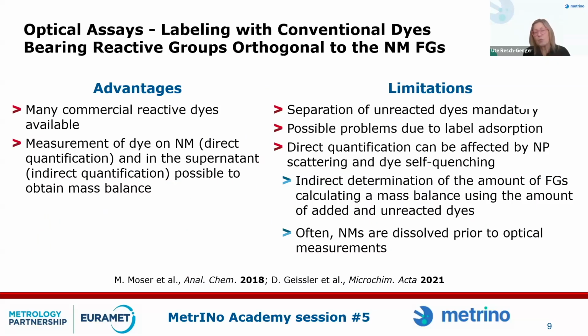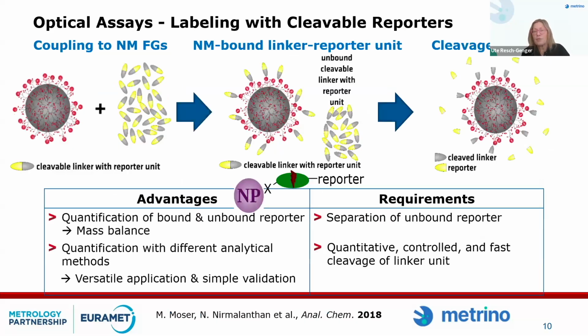What you have to keep in mind when you do this: nanoparticles can scatter, so sometimes it's easier to measure the dyes which haven't reacted with functional groups on the particle surface. Then you have an indirect determination, which nevertheless works, but there you need to know how much dye you put in in order to get this going. What can also be critical is how stable your nanomaterial is. Sometimes when you isolate your nanoparticle with a dye bound to its surface, you can just dissolve it and then measure the dye without having problems with interferences from scattering of the nanomaterial. This really depends on the optical properties of the nanomaterial, which you have to keep in mind. So these are the advantages and limitations of this type of assay, which is relatively easy.